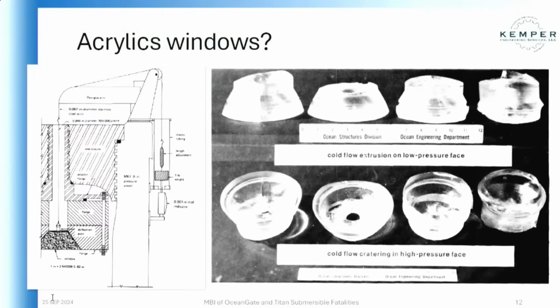And this is just to show what it was like back then. How they tested it, they had a weighted item following the shape of it, and then it was very sensitive, drawing a line on a moving graph to say it was deflecting. But the picture to the right is more of interest. There was a statement made earlier that under pressure, acrylic gets soft. No, it doesn't. It doesn't get soft, but it does flow. It's a plastic. So if you put it under enough pressure, it will deform.